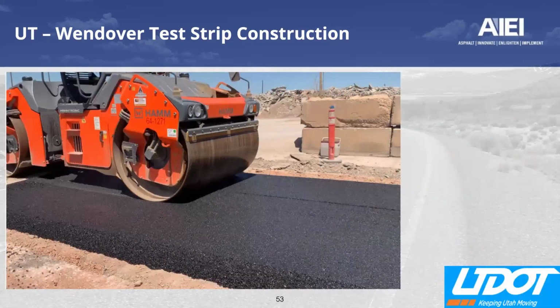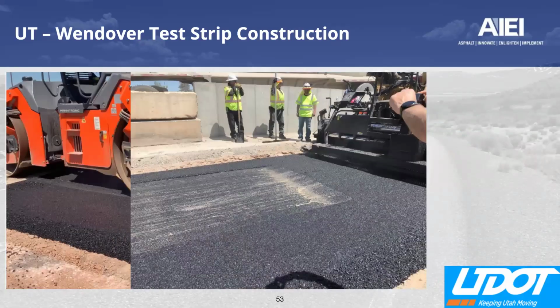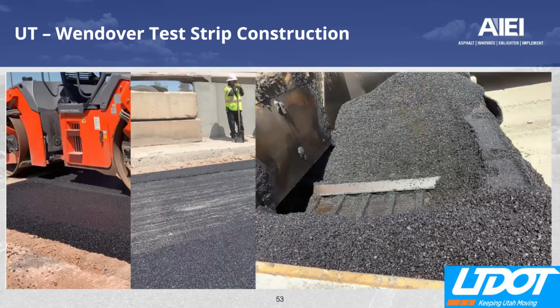The construction of that test strip went without a hitch in terms of getting density. They did run into some issues of feeding. As you may suspect, the amount of tonnage that you need to provide to the paver when you are laying a 12-foot wide mix that is going down at 7.5 inches uncompacted is very noteworthy.